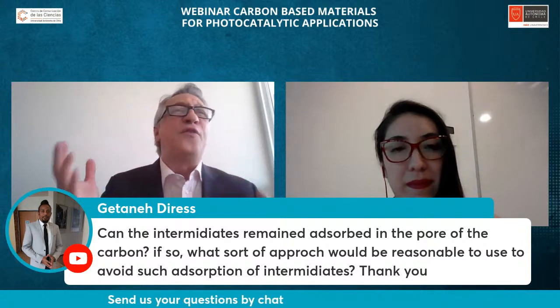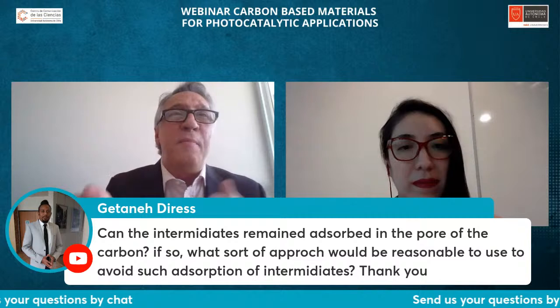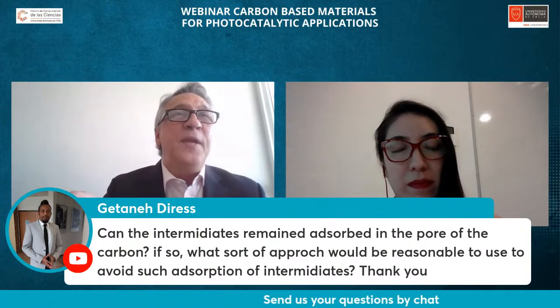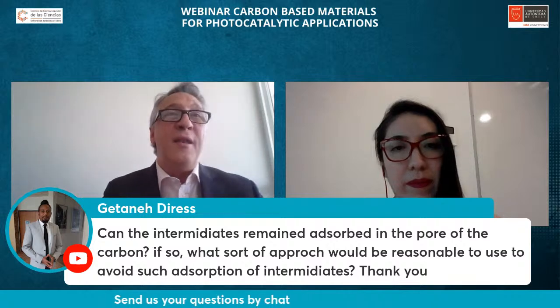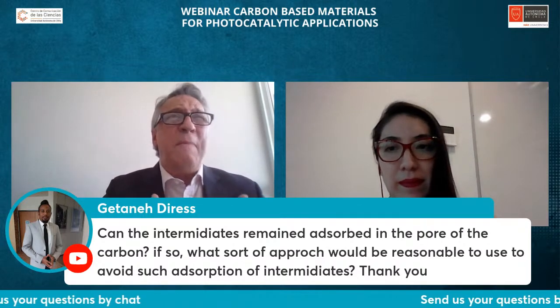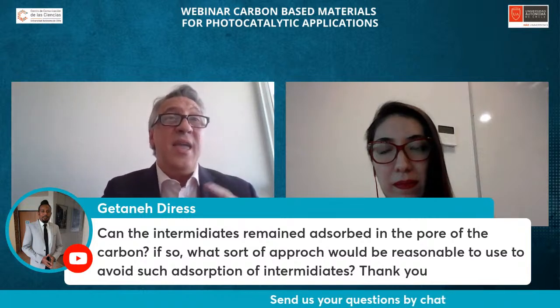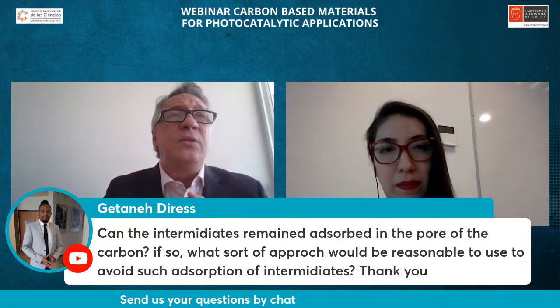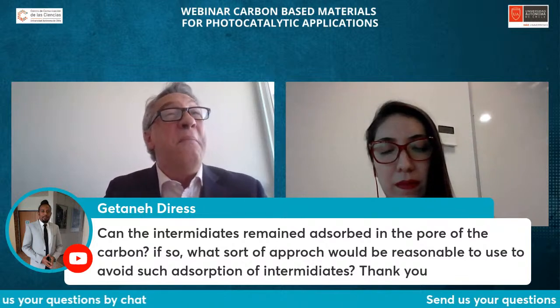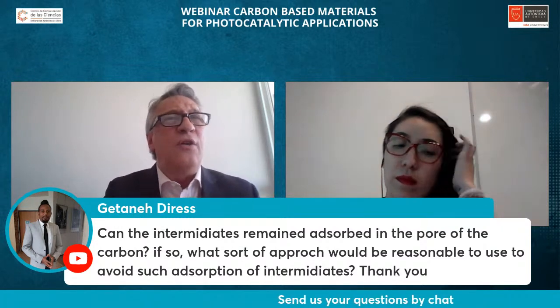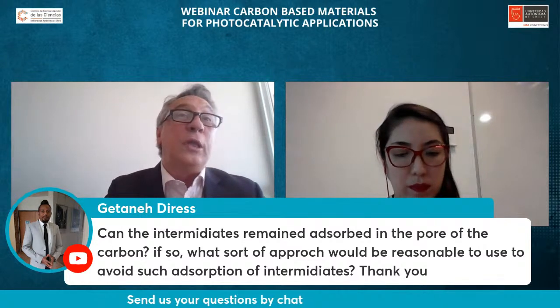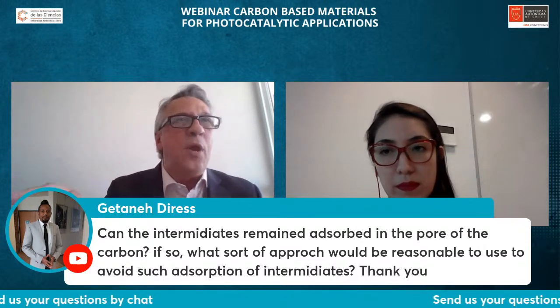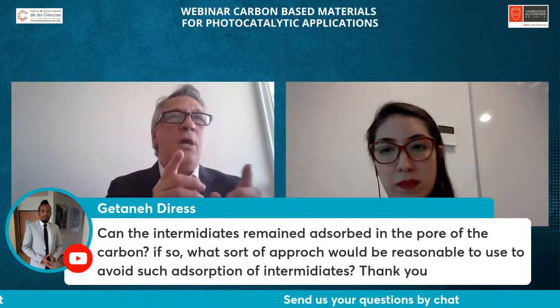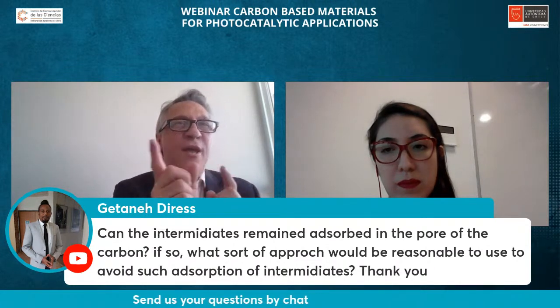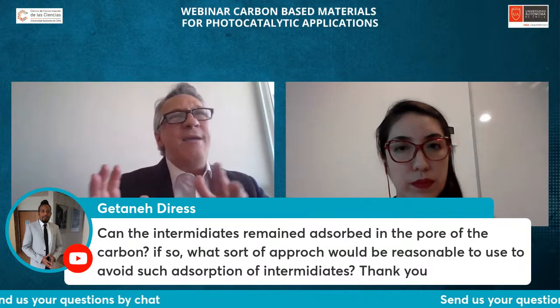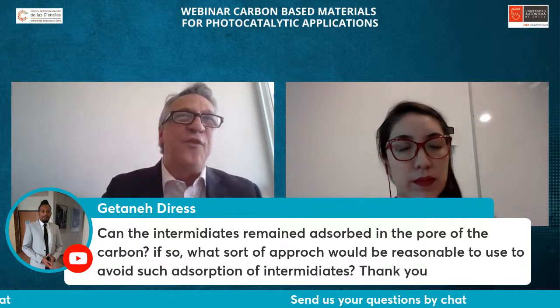Of course, there is a kind of competition. Depending on the dipolar moment of the intermediates, they can compete with the active site against the original pollutant. That's for sure. We reported in 2007 the influence of the formation of the intermediates in the degradation of phenol upon the photoactivity of titanium dioxide, in the absence and in the presence of different kinds of carbon. And depending on the polar moment of the intermediate, it is able to push the phenol out from the adsorption site.